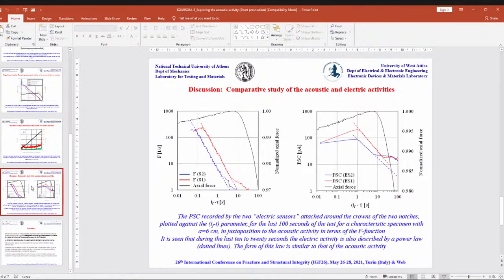At the laboratory scale, I was wondering if you have tried to apply this acoustic emission technique to loading conditions of different modes of fracture, like mode 2. In fact, when connecting epistyles, the principal loading mode is shear, yes. And we have checked experimentally such a scheme. Yes, we have very interesting qualitatively similar conclusions. The main problem is the quantitative calibration of the techniques.